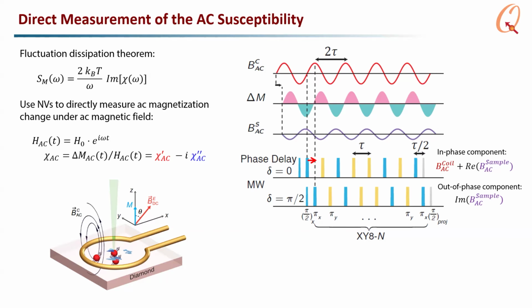the normal SQUID, MPMS SQUID AC susceptibility technique. You just have a coil that drives a global field. It's going to induce an AC magnetization change, and then we try to pick up the AC magnetic field through one of these quantum lock-in sequences, where if we time where we put the pi pulses in synchrony with the AC excitation, we measure the AC excitation and the real part of the sample response added together. And if they were ideally 90 degrees out of phase, we can measure the imaginary part of the AC magnetic response.